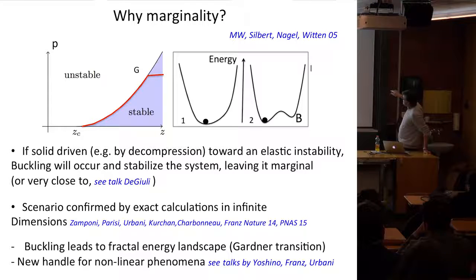So what will happen is that some modes will become unstable. And physically, the reason is very similar to the buckling of a thin rod, right? So we're thinking about a zero temperature decompression. At some point, your metastable state is going to hit this line. When you do so, modes become unstable. Just like buckling, you would expect that this instability will take place, but will not lead you to infinity. You will have nonlinear terms that actually stabilize you.